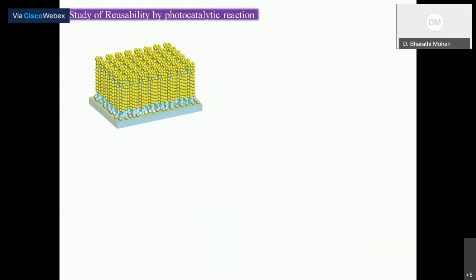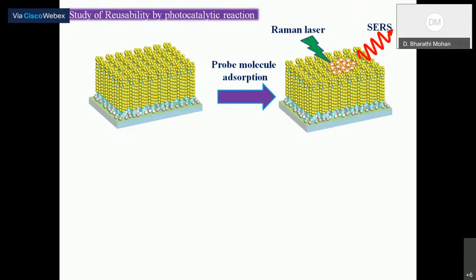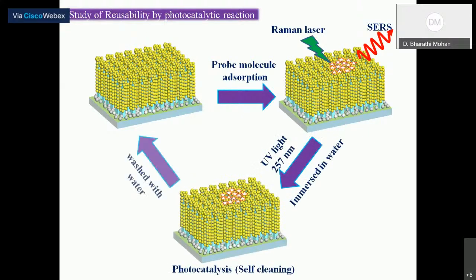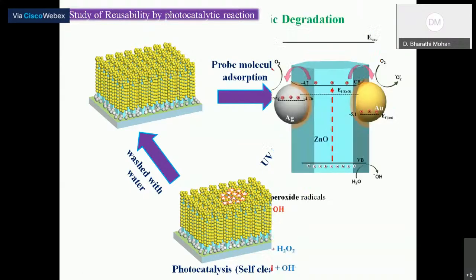So we have done the reusability test by applying the photocatalytic reaction. And in this case, what we have done, after drop casting the probe molecules and recording the SERS spectra, we dipped this entire thing in the water and shined with light with the wavelength of 257 nanometer to wash away the entire rhodamine 6G molecules from the substrate, and the substrate becomes fresh again. And with the help of the photocatalytic reaction, we can reuse the same substrate multiple times. So this is the advantage of the 3D hybrid nanostructure.